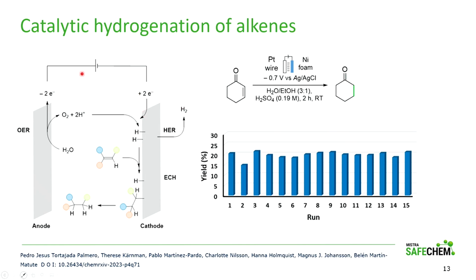This is, for those that are interested, a little bit more detail of how the reaction happens. So the protons react with the nickel foam and 2 electrons, and you form these nickel hydrides, and these nickel hydrides are transferred to the unsaturated carbon-carbon bond, providing the final saturated compound. And then at the anode, we have the oxygen evolution reaction.